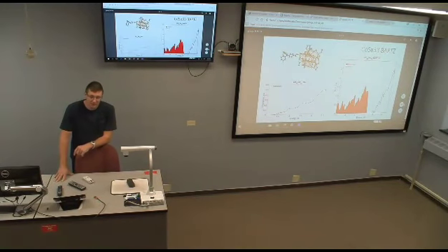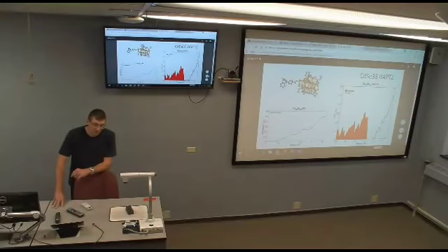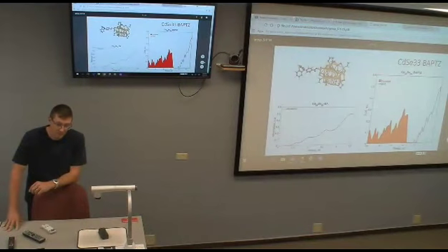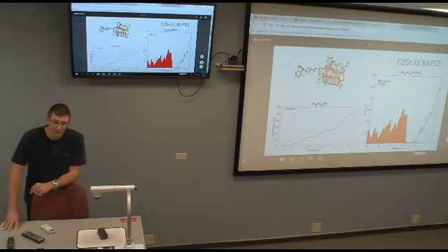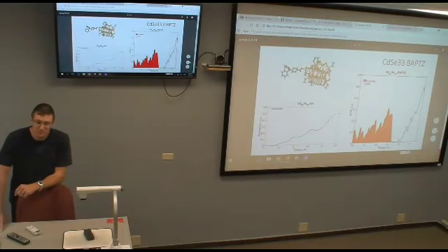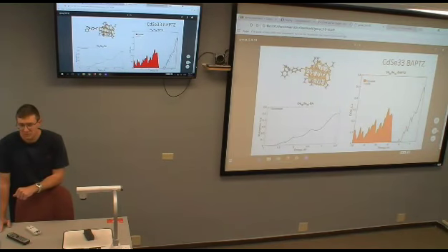I would say in your case, you have a problem with functionals. You cannot apply the same procedure in Gaussian to compare the correlated versus non-correlated band gap. And here you have different functionals, so that's why I would say you probably need to run two jobs: TD-DFT with the PBE functional and TD-DFT with a hybrid functional, and then see the effect of the hybrid functional, because the effect might not be just increasing the gap, but also you might have different nature of your orbitals.